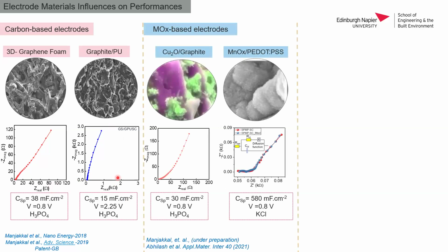Another version of the electrode which I am developing in a flexible version is the graphite or a metal oxide based electrode, or a metal oxide with a composite, like a metal oxide with PEDOT:PSS, or a metal oxide with graphite. So you can see from here that there is a copper oxide with graphite, which has a different performance as compared to the other devices, where the capacitance varies depending on the voltage or the electrolyte.